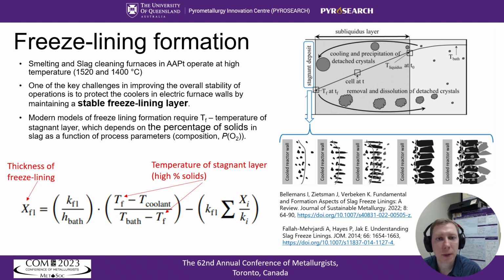Improvements in the stability of freeze lining are very important for the stability of operations and throughput. Freeze lining is a stagnant layer of partially solidified slag, which protects furnace walls from corrosion by molten phases at extremely high temperatures. It is achieved by active cooling of the furnace walls and controlled by the heat flux as well as solidification properties of slag. An example of mathematical model predicting the thickness of freeze lining is shown on the slide.